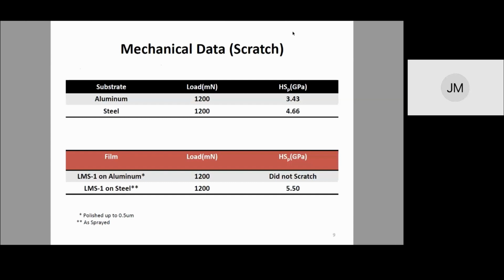slurry, which removed the surface characteristics of the films, which are cratered and significantly rougher than the bulk of the film, which gives it a higher resistance to abrasion. So that film did not scratch.